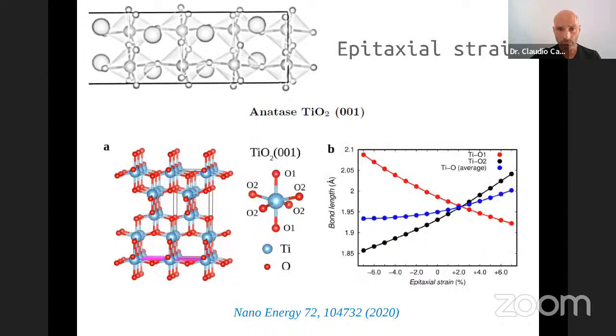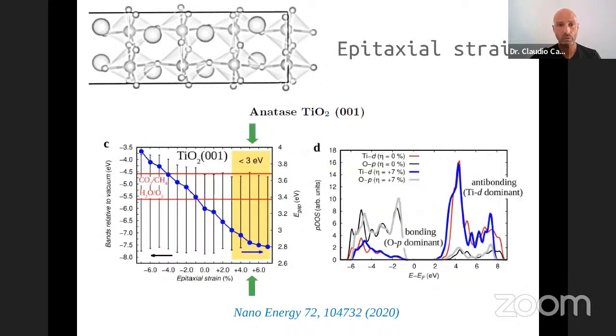water splitting reaction. We did the same for another archetypal photocatalyst, titanium dioxide, which was actually the first photocatalyst reported for the water splitting reaction, a long time ago. In that case, we did the same kind of calculations, and we found a quite similar trend in the energy band gap, right? So essentially, as you increase the compressive strain, the band gap increases, whereas when you go to the tensile strain side, the band gap is reduced, right?